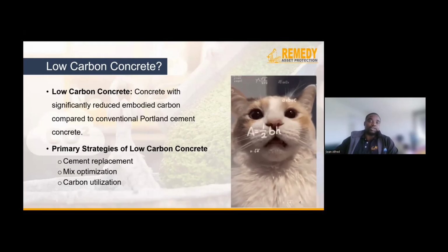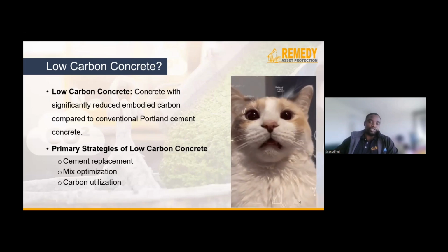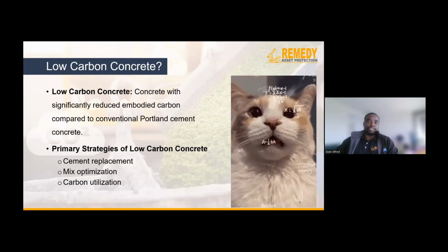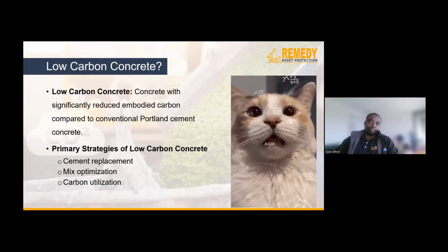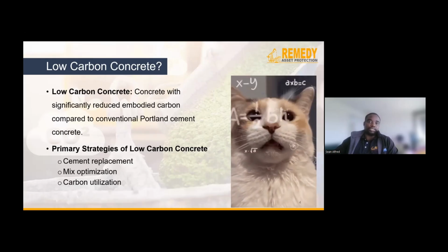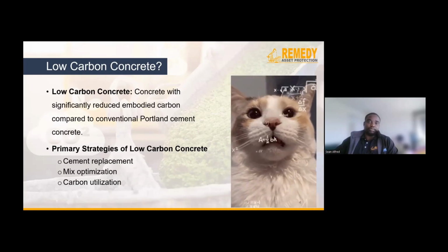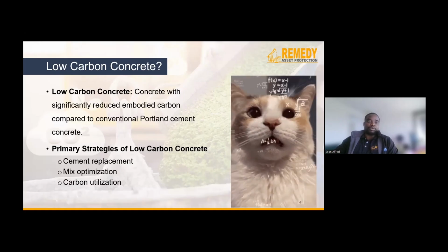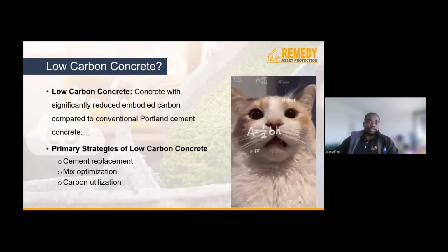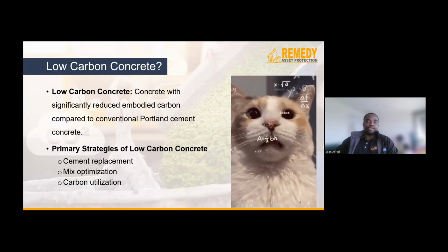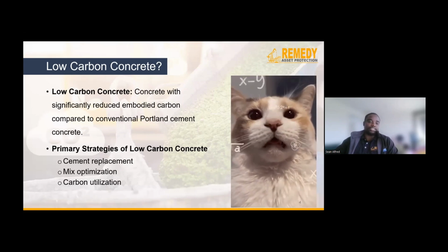We can basically say low carbon concrete is concrete with significantly reduced embodied carbon, which encompasses all emissions of the entire life cycle of the material, compared to, for example, the conventional Portland cement concrete. But this isn't just one aspect, and it's a family of approaches that all feed into the emissions that come from the material itself. Now, the primary strategies include cement replacement using supplementary cementitious materials and alternative binders like alkali activated materials or calcium sulfoaluminate systems.